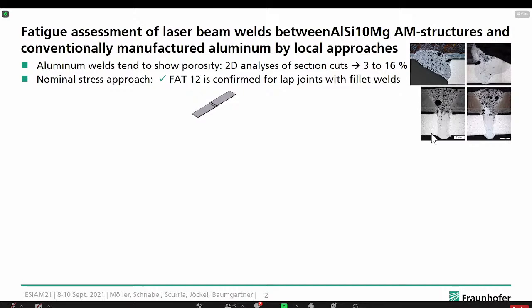Yeah, I didn't quite see the chemical content for these 2 alloys that were welded. I don't think they were exactly the same, but could it be that the welding process parameters are not well optimized for the AM side, but perfectly optimized for the conventional side? Yes, for sure. This might be a next point to investigate, since there is not much experience on welding of AlSi10Mg. There is some experience from cast AlSi10Mg, but not so much compared to the conventional one. So the starting point was to use parameters which fit the conventional one.